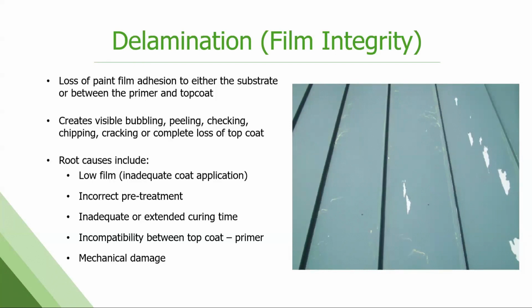The biggest one is mechanical damage. Scratches that have occurred, damage that has occurred, you get an opening in the paint system. Now you have a spot where water, ice, other things can get in there and start peeling that paint away. The example I have here, I don't know if you can notice, there is a very distinct vertical line where each of this peeling is starting from. And what this most likely was, when they installed this building, dragging the corner of another panel up that panel and leaving that scratch. And then over time, that's just an opening where the paint can come apart.